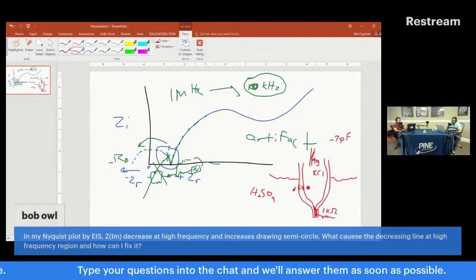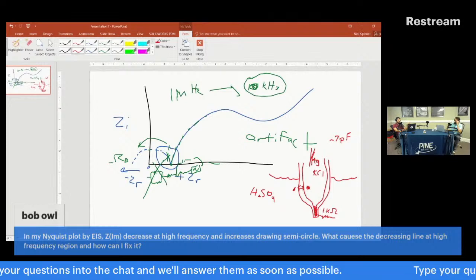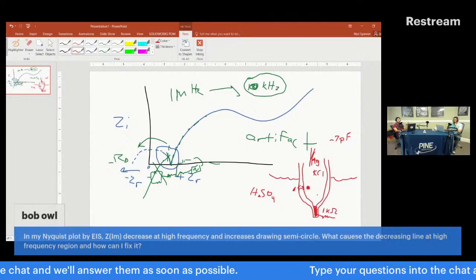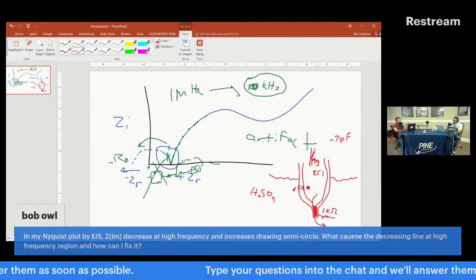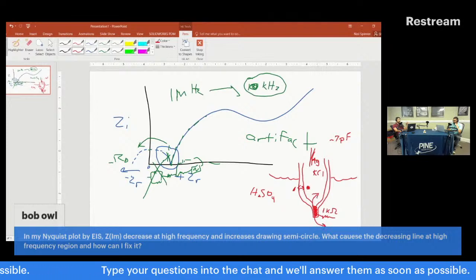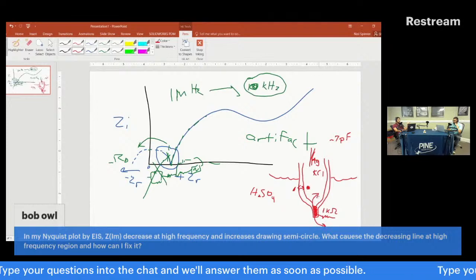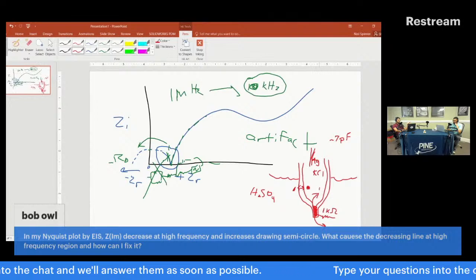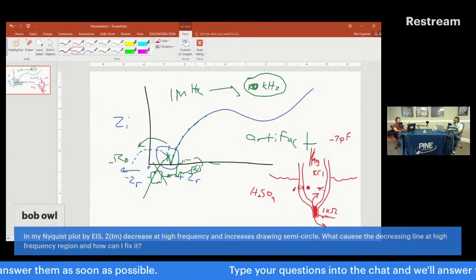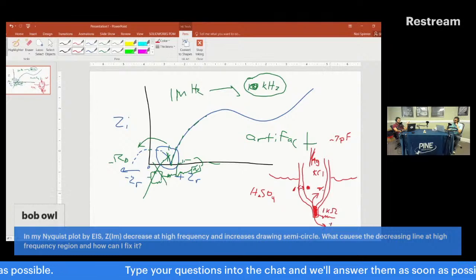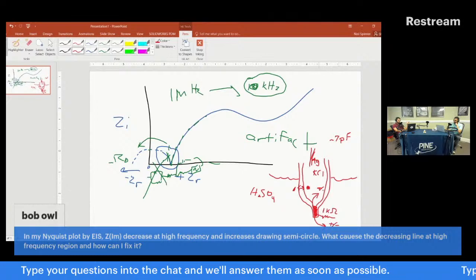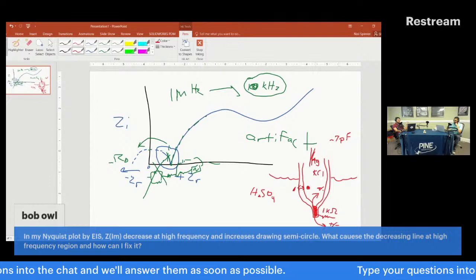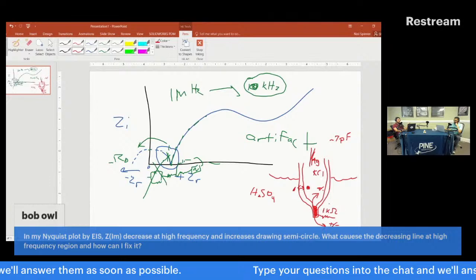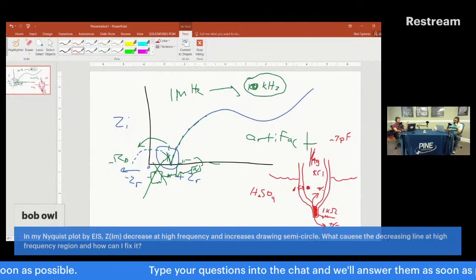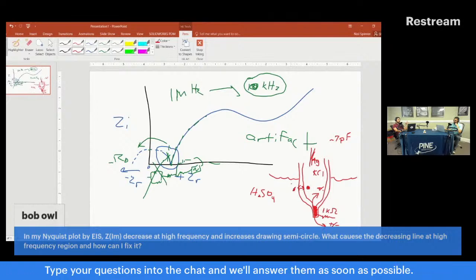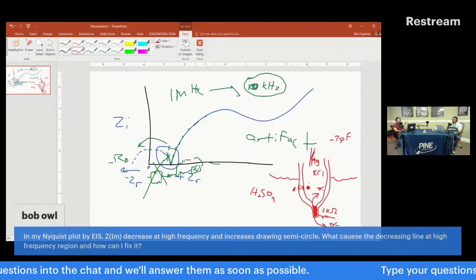It can go through the frit. That's what the frit's for. That's the main purpose of the reference electrode in an electrochemistry experiment. There's actually ionic flow here. Ions move very slowly, not fast, because you don't want heavy leakage. But generally speaking, ions, plus or minus, K or Cl, can communicate through this frit with a resistance of about 1 kilo ohm or so. But there's another way to communicate between inside and outside of the solution. It's through the glass, and it's this capacitance.